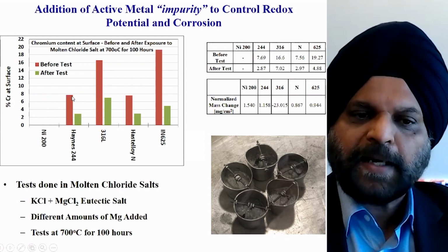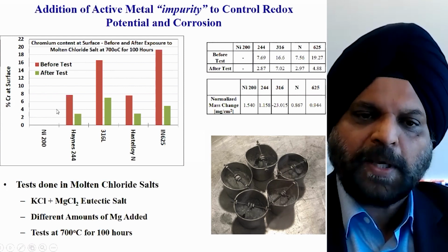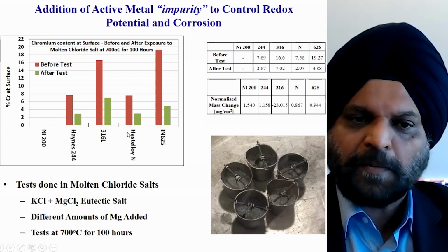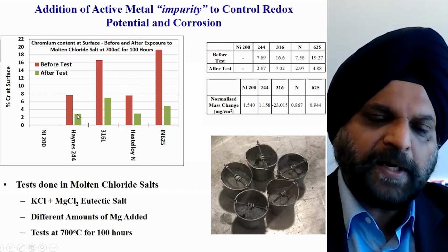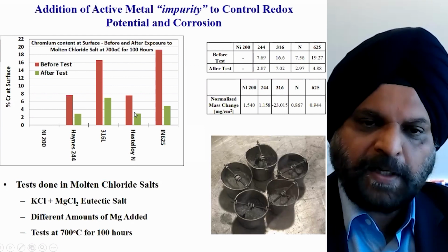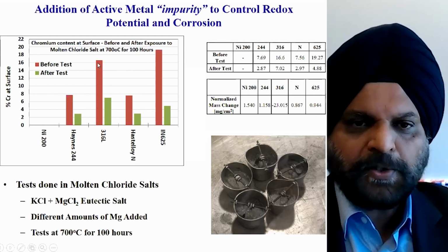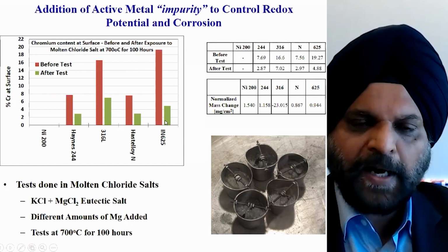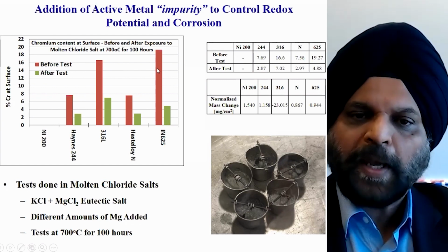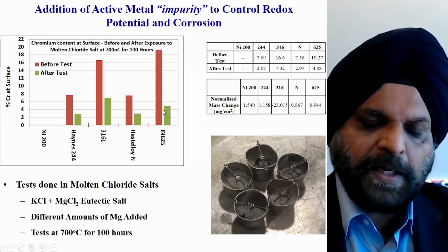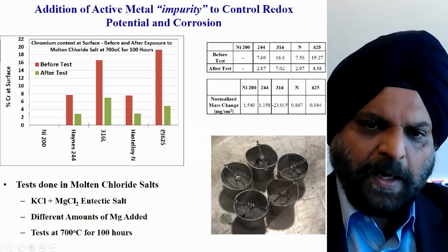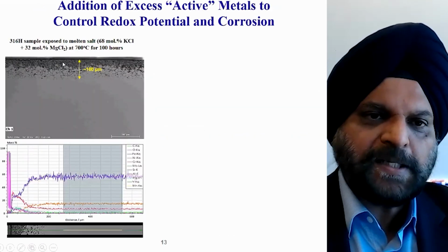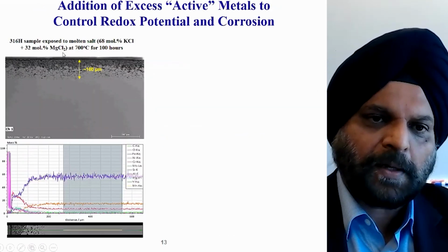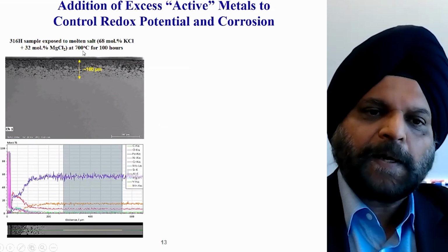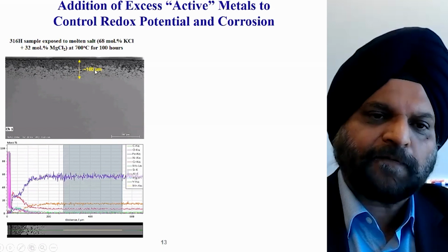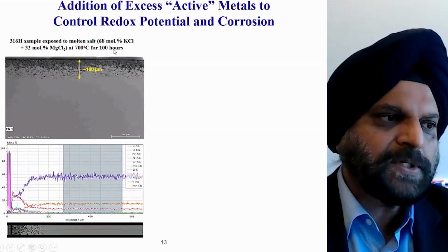You can see that Haynes 244 and Hastelloy N behave in exactly the same way. They have similar amounts of chromium, and after the test there is a similar decrease in chromium content at the surface. Now 316 and Inconel 625 have higher amounts of chromium to start with, and the percentage decrease in chromium content is significant. If you look at the sample of 316H exposed to chloride salt, you see about 180 microns of intergranular attack in 100 hours in this particular salt.